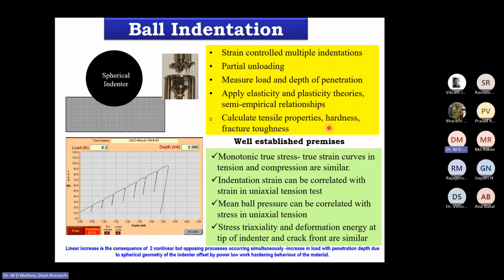And when you apply the ball, there is a pressure, and the mean ball pressure can be correlated with the stress in uniaxial tension. And another important assumption is that the stress triaxiality and the deformation energy at the tip of the indenter is similar to what exists at the tip of a crack in a standard fracture mechanics test. So you have here a ball, you are driving it into the material, you measure the depth of penetration, you measure the corresponding load, but this process is repeated multiple times, and you have the depth of penetration and load data. From that, you are generating the stress strain curve.